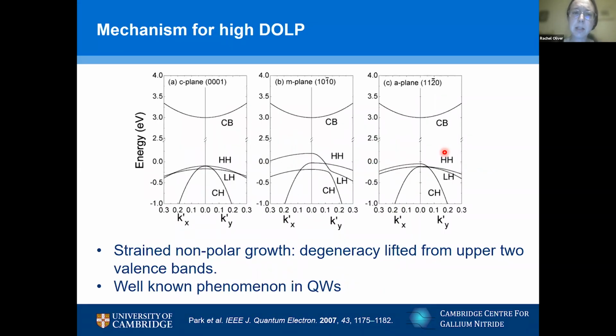Why do we get this high degree of polarization? Well, it's to do with the strain in the quantum dot and the nature of the crystal plane. So the C plane, where we normally grow, has a symmetric strain state. You only really have to worry about the difference between the a parameter of the film and the a parameter of the substrate, and it's symmetrically strained. And in that case, you can see that we have this overlap between different hole bands.